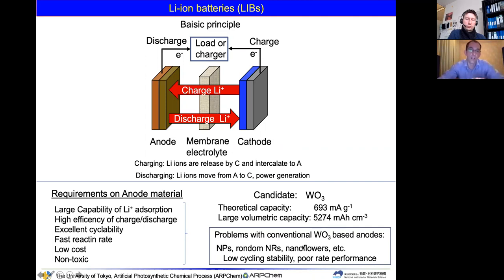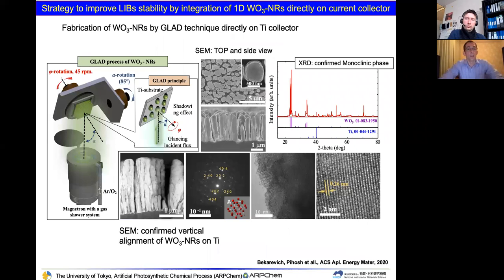However, there is a problem with conventional tungsten oxide based anodes, for example in nanoparticulate systems, random nanorods, nanoflowers, or thin films, because there is low cycling stability and poor rate performance. So for that reason, we fabricated, with Dr. Bakirevich, tungsten oxide nanorods directly on the current collector.